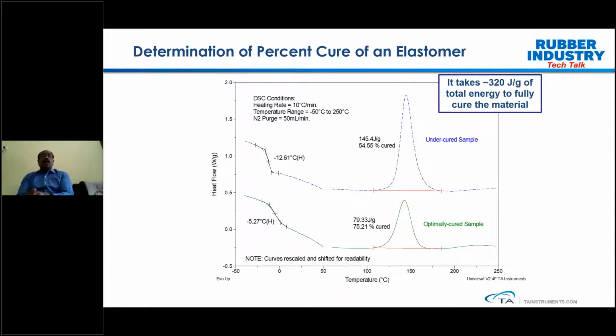Whereas the blue compound has a lower Tg as well as a higher residual cure. This is the second time we are keeping the sample on the DSC, where in the second run we are seeing this thermogram behavior. So coming back to the blue curve, when you account the energy, which is higher, 145.4, if you take the ratio, the blue color compound has cured only 55%. So that is the reason we say that the sample is undercured, and that also reflects in your glass transition, which is at the lower temperature. So this way you can see how DSC is really helpful to understand things.